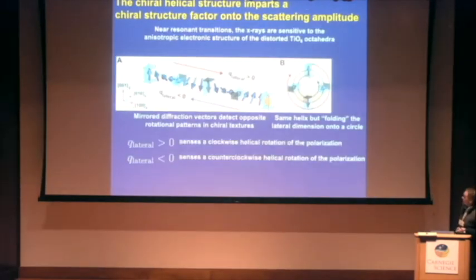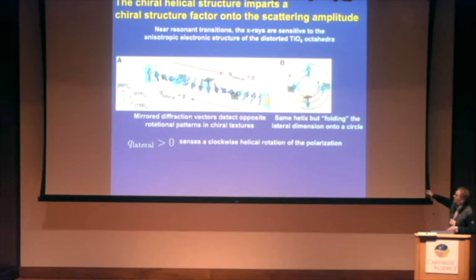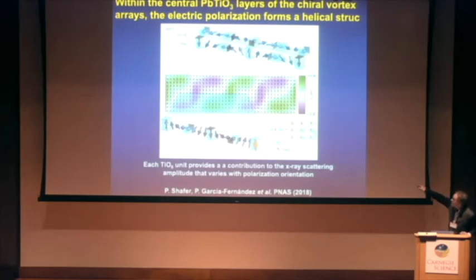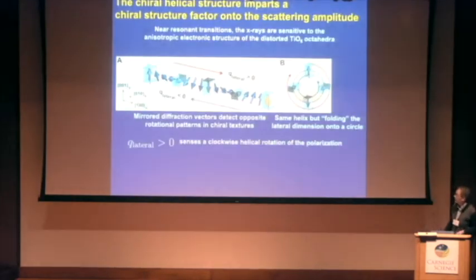So just the last slide. The origin of this chirality can be traced back to the presence of a helical structure at the center of the clockwise, counterclockwise vortices. If we plot a line here and look at how the polarization is changing, we can see that we have a helical structure.